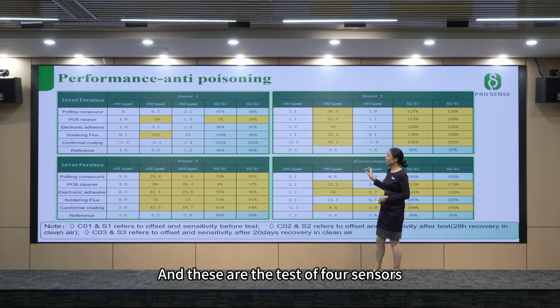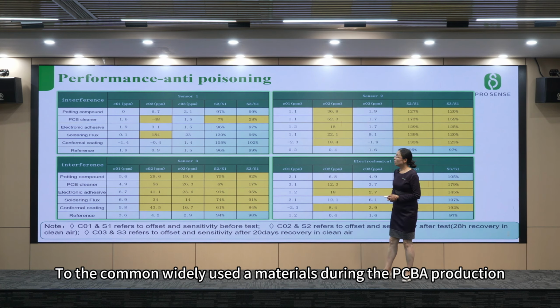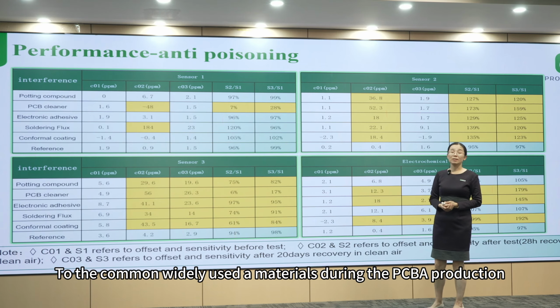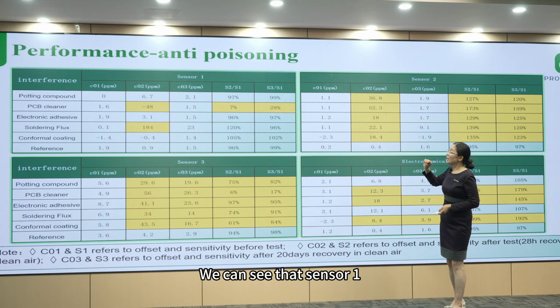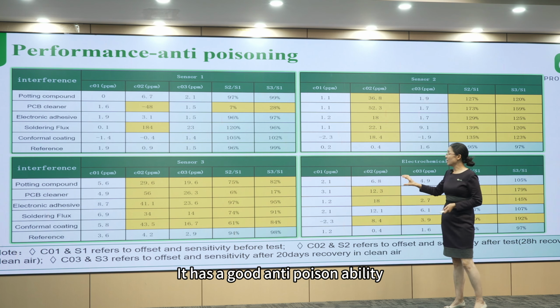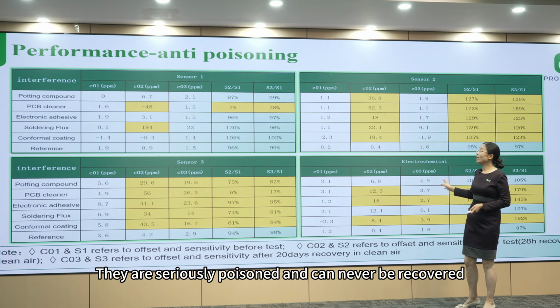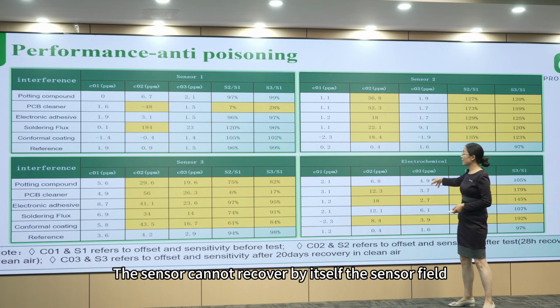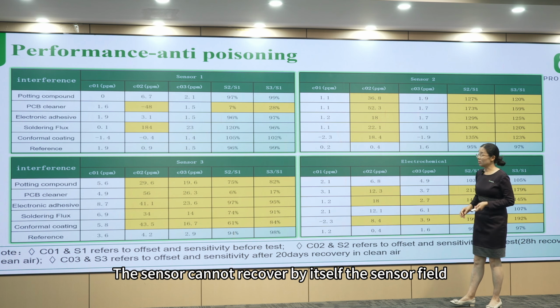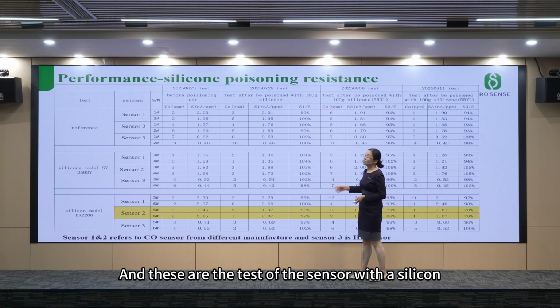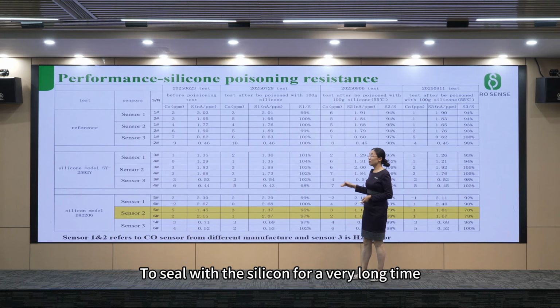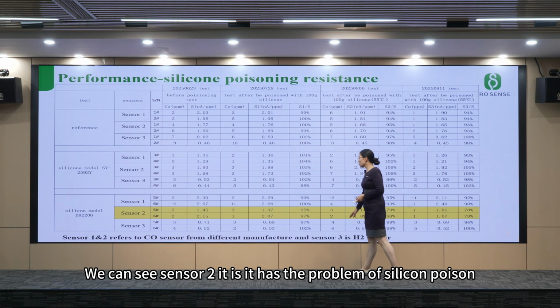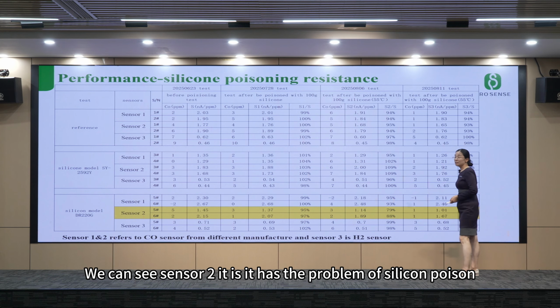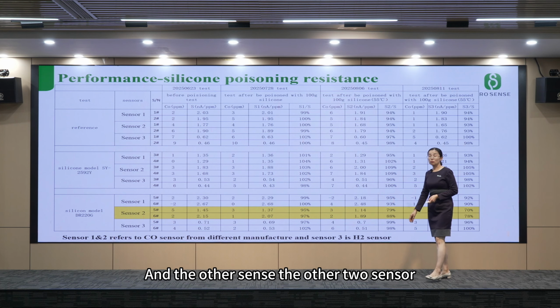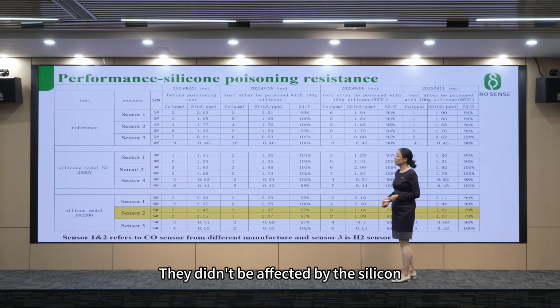And these are the tests of 4 sensors against common, widely used materials during PCBA production. We can see that sensor 1 has good anti-poison ability, and the other 3 are seriously poisoned and can never be recovered. The sensor cannot recover by itself. The sensor failed. And these are the tests of the sensors sealed with silicon for a very long time, more than 1 month. We can see sensor 2 has the problem of silicon poison, and the other 2 sensors were not affected by the silicon.